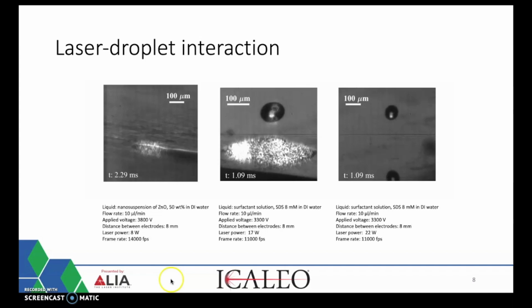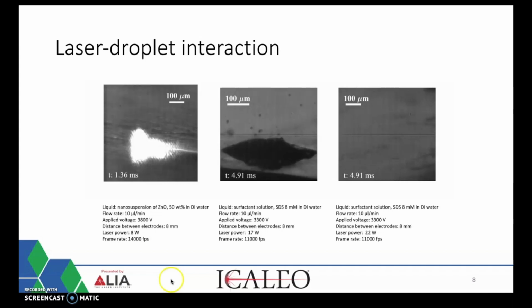After using high-speed imaging and image processing, results suggest that at the impact of nanosuspension microdroplet onto the surface that is heated above the boiling point of the liquid, the microdroplet either instantly boils after collision on the surface or, without any contact with the surface, develops a Leidenfrost vapor layer beneath the liquid surface and bounces back. On the other hand, if the localized temperature of the droplet impingement spot is below the boiling point, the nanosuspension microdroplet spreads radially, forming a film that gently evaporates.